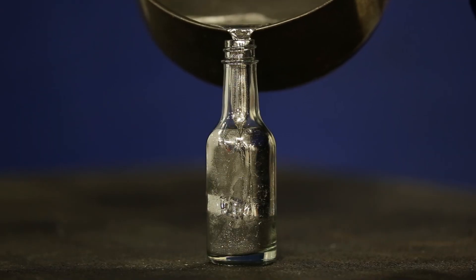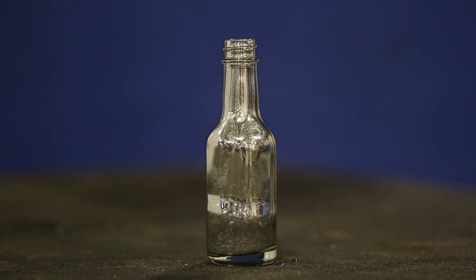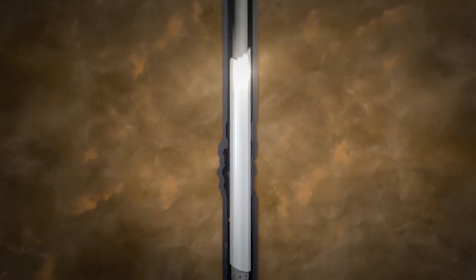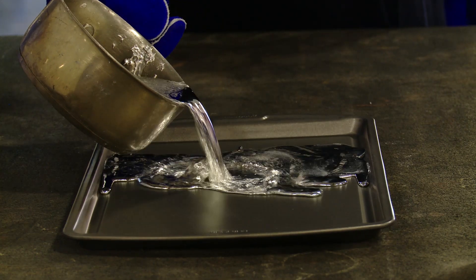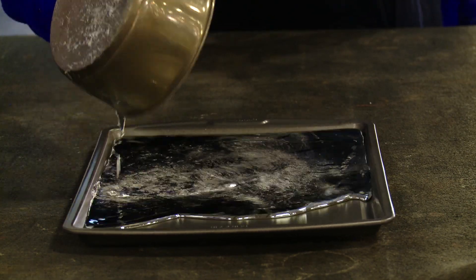The bismuth alloy is quite unique in its properties. It expands on solidification, very similar to water when it changes to ice — we get a three percent expansion, and we use that expansion downhole to create a gas-tight seal. It also has a viscosity very similar to water, which is very useful, especially when trying to seal off through a sand screen where we can get it to flow through a 200 micron sand screen.